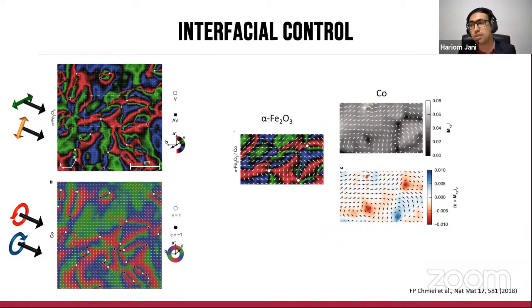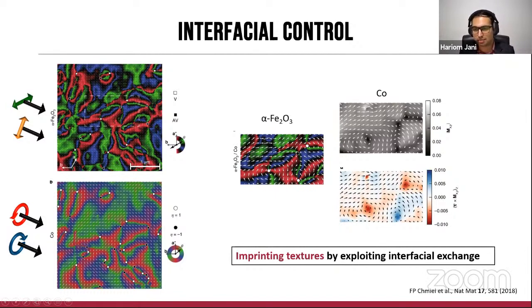But with platinum, we actually have very systematically tunable and reversible processes that are obtained in the system here. What is key to note is that if the ferromagnetic overlayer can be grown carefully and the antiferromagnetic layer appropriately doped, it may be possible to actually realize a ferromagnet-antiferromagnet interface, which would still have the Morin transition and still recreate all these phenomenologies in a reversible process, which then is very critical for any kind of implementations. And basically, this is purely because of the interfacial exchange.